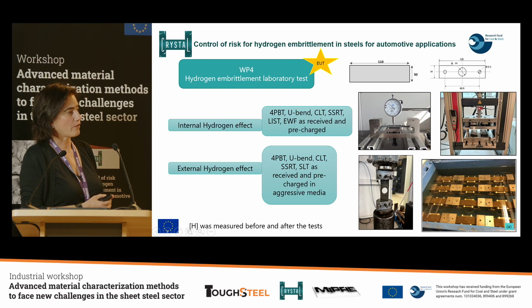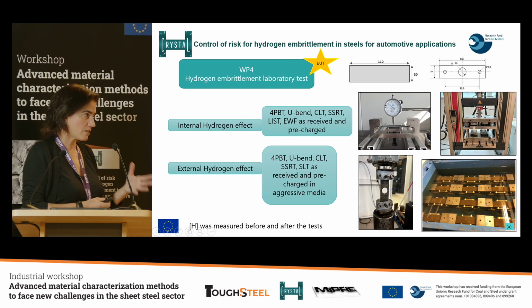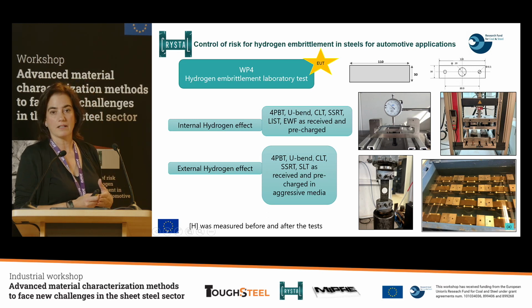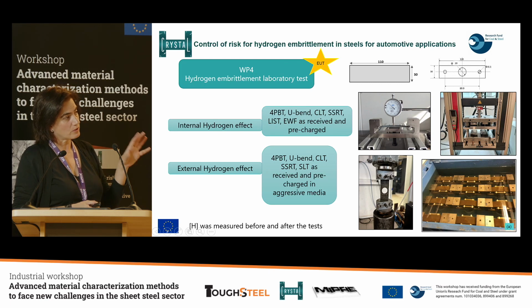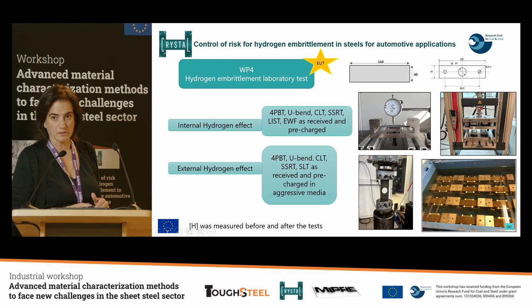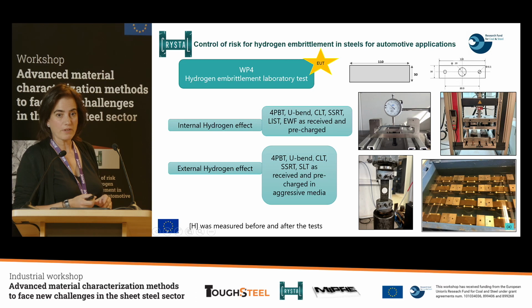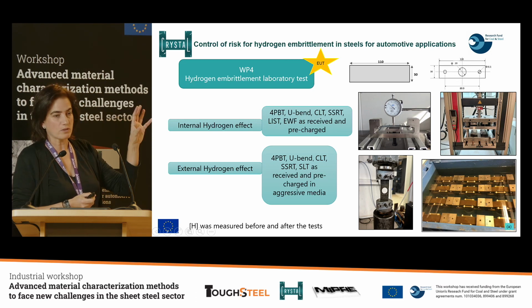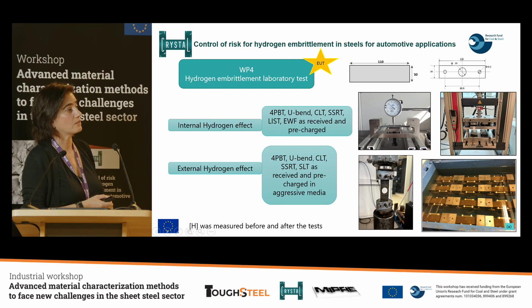In the case of external hydrogen, we perform 4-point bending test, U-bend, constant load test, slow strain rate test, and step load test, also in as-received condition, after pre-charging, and in aggressive media. We decided to test these samples in immersion and in salt spray test. Anis Aouafi, later on, will explain the most important results of this work package.